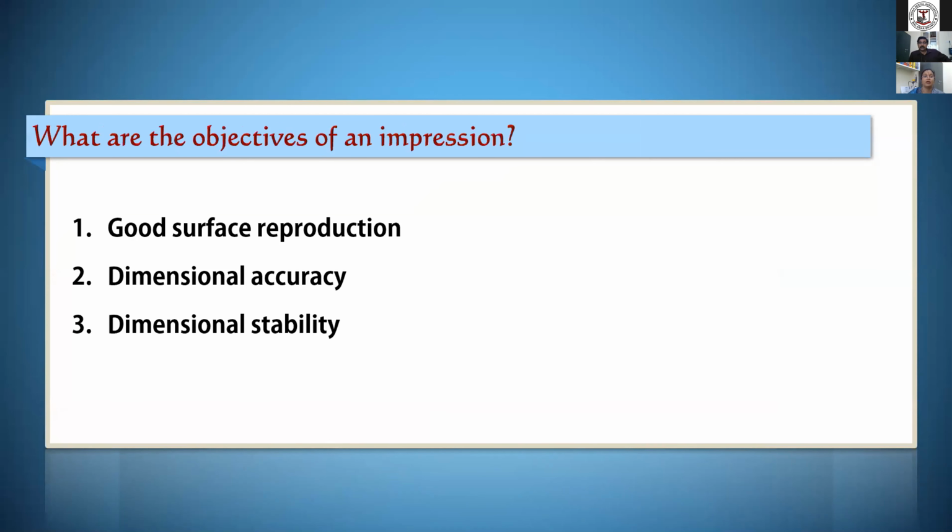And the surface reproducibility of type 4 gypsum cast is 20 microns if you're using it along with elastomeric impression materials. An alginate impression material, whereas, can only record a line of 50 microns. And moreover, the surface reproducibility of gypsum on an alginate impression is greater than 100 microns due to the inhibition of the surface layer by the calcium alginate. This makes an immense effect on the accuracy of fit of the prosthesis fabricated on dies made from gypsum poured in alginate impressions compared to that of elastomer.